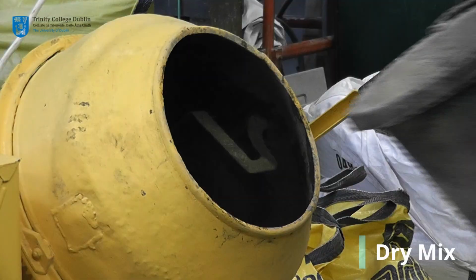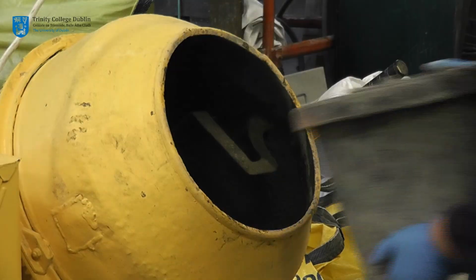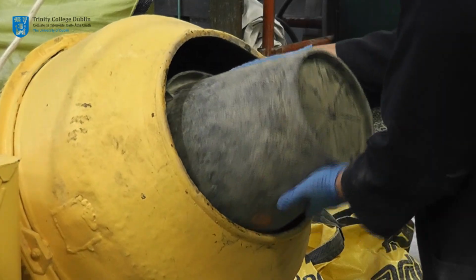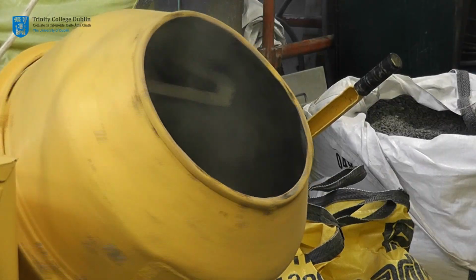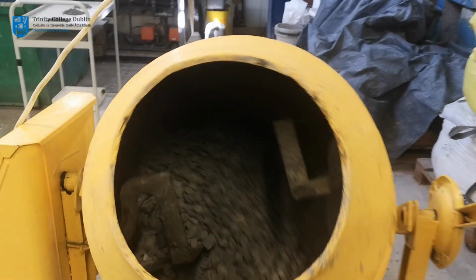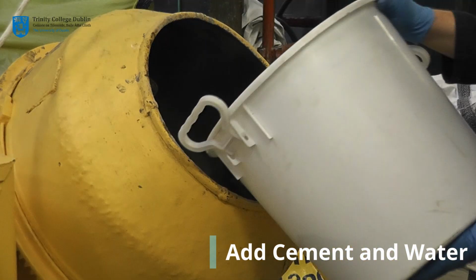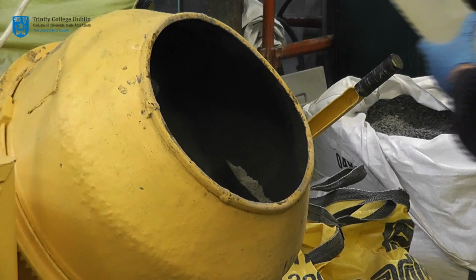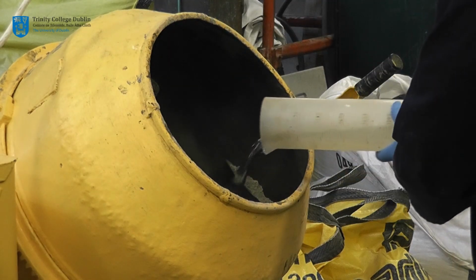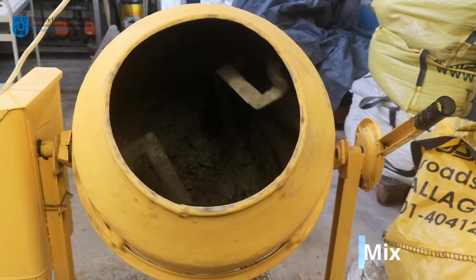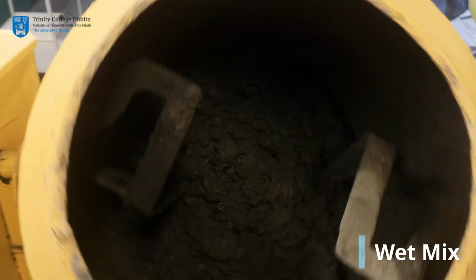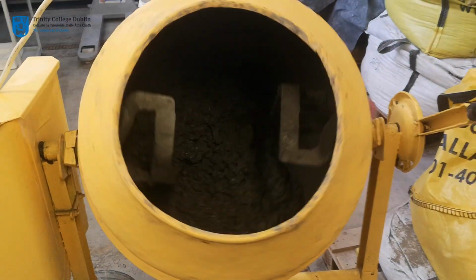The 20mm and 10mm coarse aggregates, plus the fine aggregate, are added to the drum. The aggregates are mixed for approximately 30 seconds. The cement and water are then added to the mixer. With all of the constituents now in the mixer, wet mixing can commence. The concrete is mixed for approximately 5 minutes. It is then left for 10 minutes so that the water may be absorbed by the aggregates and cement. It is then briefly mixed again before discharging.